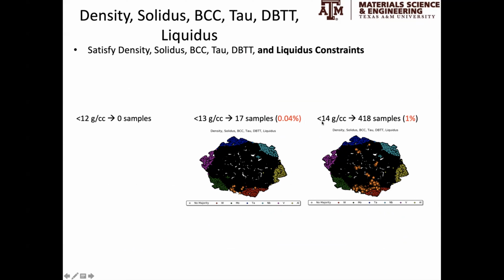And not surprisingly, again, the region that satisfies this very tight constraint is really close to the tungsten corner of this two-dimensional projection of the refractory high entropy alloy space.